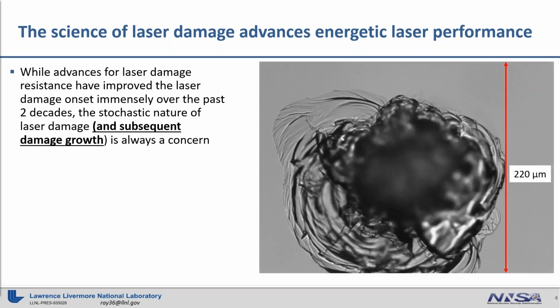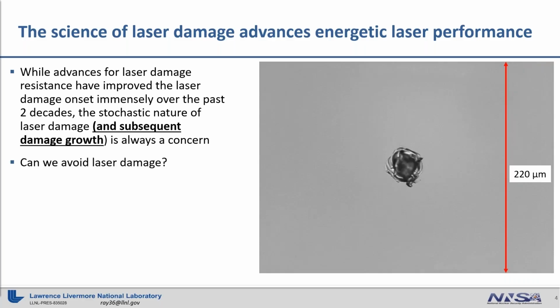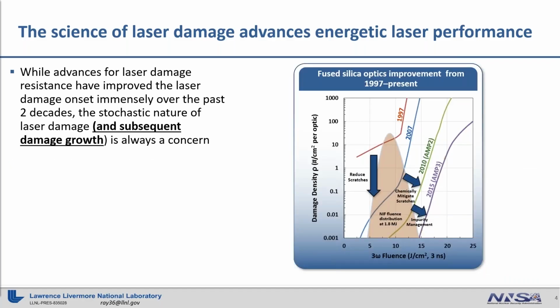Laser damage initiation, actually, if you can go back one click. So the red curve is the initiation density, or how many damage sites initiate per square centimeter at the fluence shown on the x-axis in 1997. And if we move to more recent times in 2015, then we go to that purple curve, which shifts down and to the right. And that's really the space that we want to be in. But the stochastic nature of laser damage tells us that there will always be some laser damage initiation.